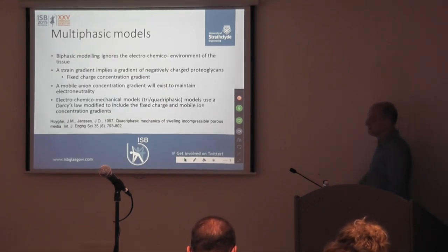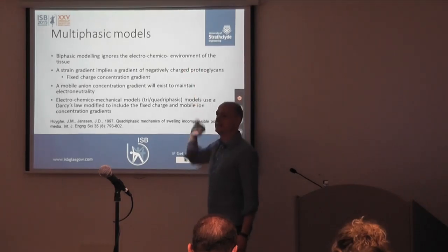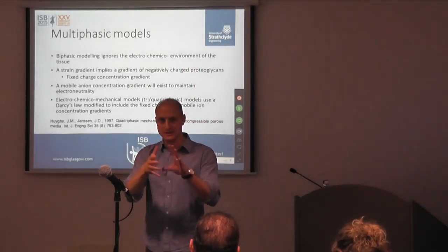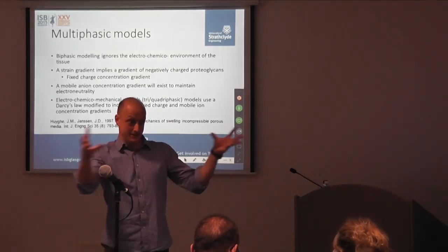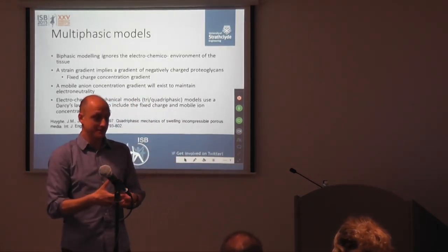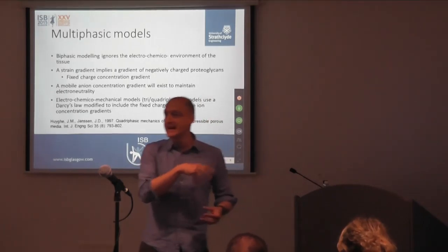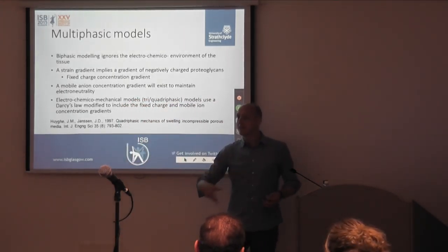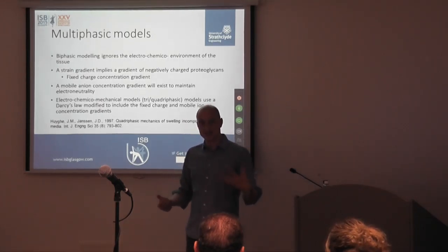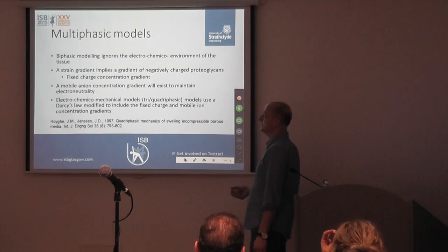The biphasic modelling ignores these GAGs. There's no concept of these GAGs. And the reason it sucks the fluid up is that these GAGs are negatively charged, and there's an osmotic pressure wanting to suck up the fluid. That's due to the negative charges of these proteoglycans.